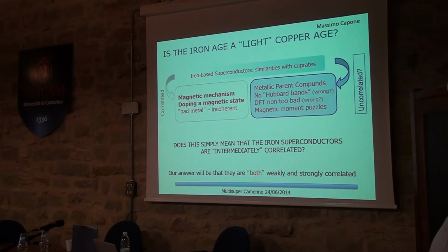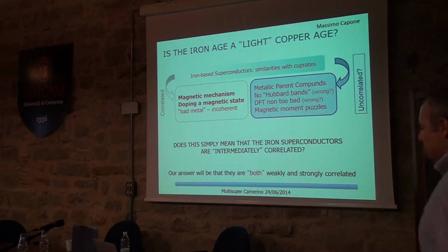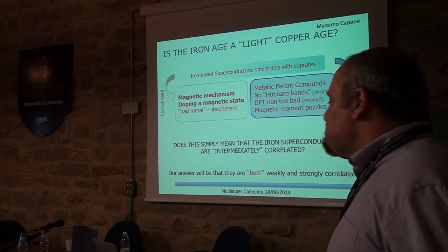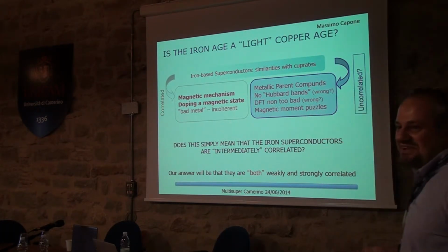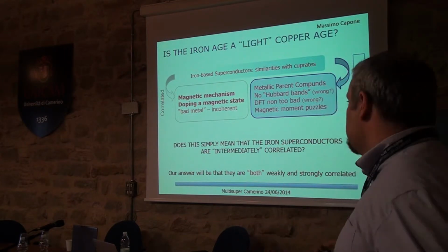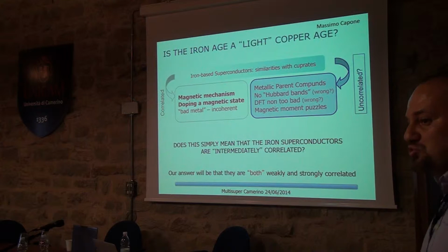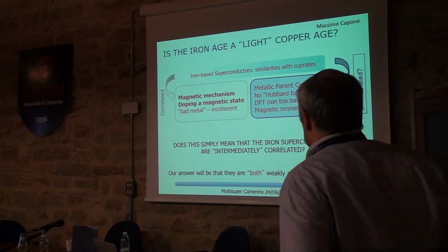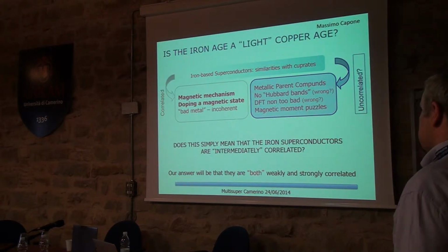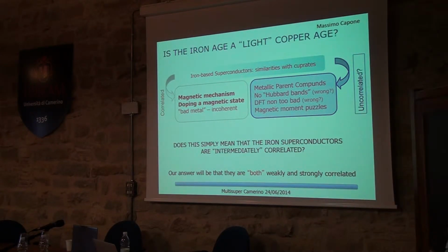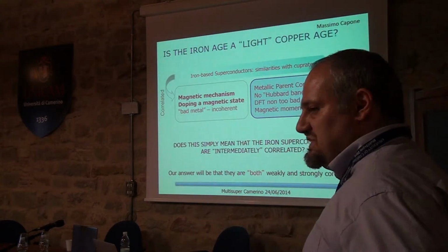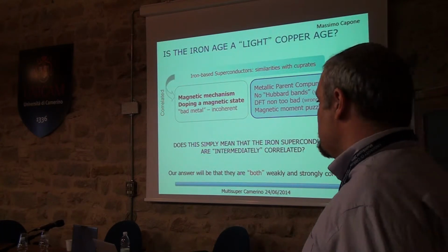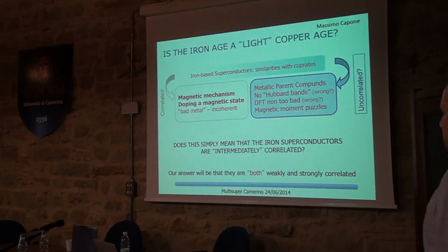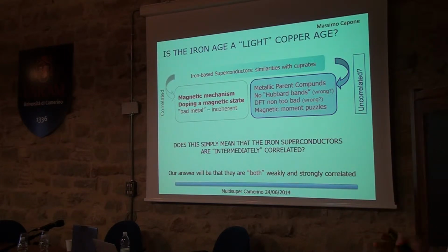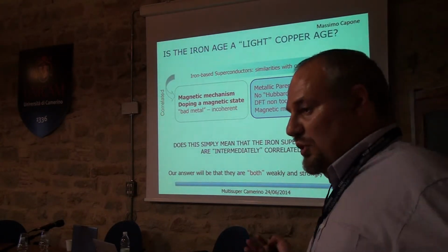And the other maybe wrong thing is that there is a widespread feeling that density functional theory is not too bad. It describes the band structure quite well, and still, once again, I have to invoke Sergei, who was showing that at least the cartoon that came out from the first DFT calculation doesn't seem to be the right cartoon to play with to understand what's really measured in these materials. And then there is something that I will not comment too much about. We could quote some puzzles about the magnetic moment. We have some conflicting evidence about small and large magnetic moments, which might have to do with the dynamics of them, and so on and so forth. Yet, the bottom line is that there is no very strong evidence for clear, well-formed magnetic moments, which would be one of the main fingerprints of strong correlations.